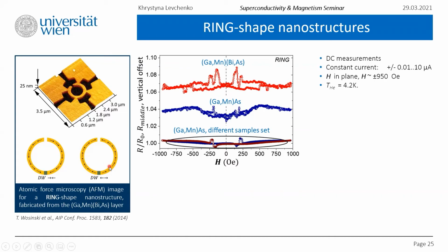So domain walls are the regions of inhomogeneous magnetization, and they separate ferromagnetic domains of homogeneous magnetization. When charge carriers are passing through domain walls in nanostructures, they exhibit spin-dependent scattering because there is reorientation from this direction to this direction. And this leads to an additional contribution to the resistance, and that is seen in our measurements.